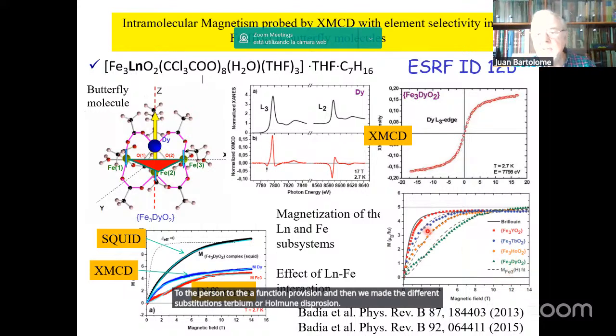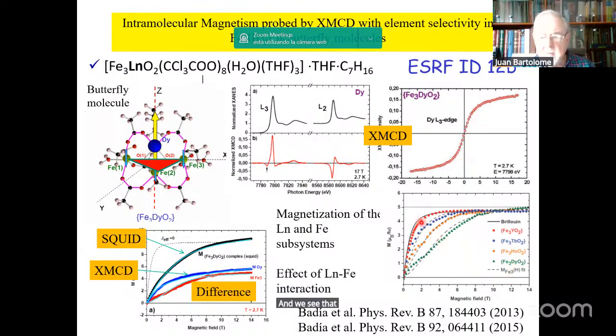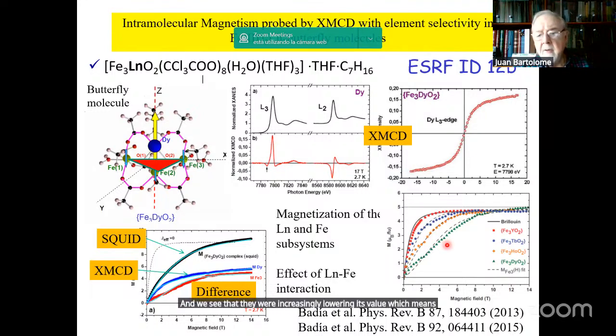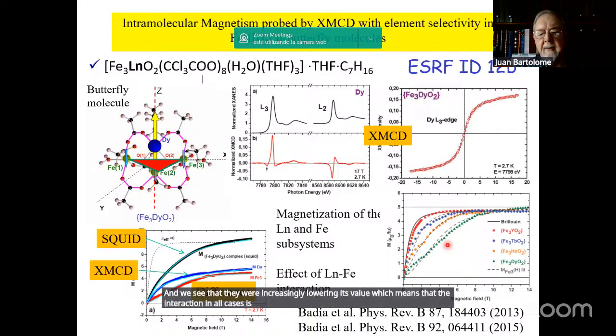In the case of yttrium, which is non-magnetic, which gives then the behavior of the pure iron triangle, compared to the Brillouin function prediction. And then we made the different substitutions of terbium, holmium, dysprosium, and we see that they were increasingly lowering its value, which means that the interaction in all cases is antiferromagnetic.